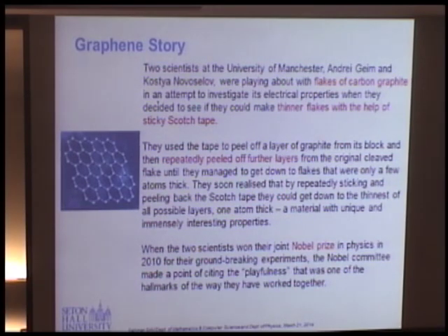They went almost to one-atom thickness because graphite has the graphene structure built up in layers. You cannot do it with other materials, but you can with graphite. They figured out that's graphene, and they got the Nobel Prize for that. I think this is the fastest Nobel Prize in physics that I know of. It was a very short discovery, and they got the Nobel Prize in 2010. Graphene is good for the future of semiconductors because you can go to one atom thickness. It's so tough. If you can make a transistor from graphene, I was talking about small thicknesses, and 3 atoms is not good for silicon. You can go almost to atom size. So that's why it's hot.